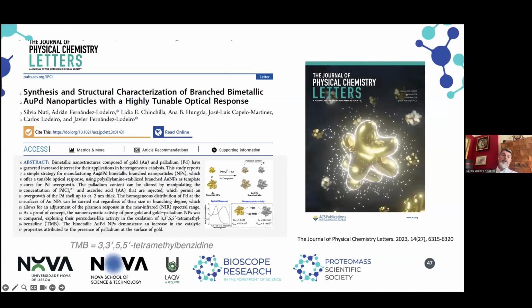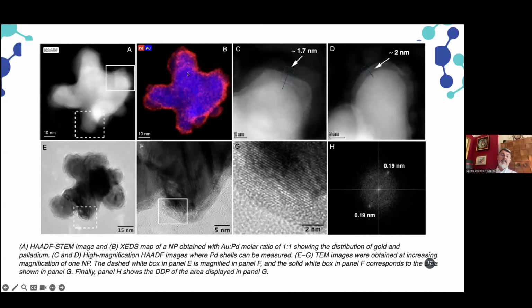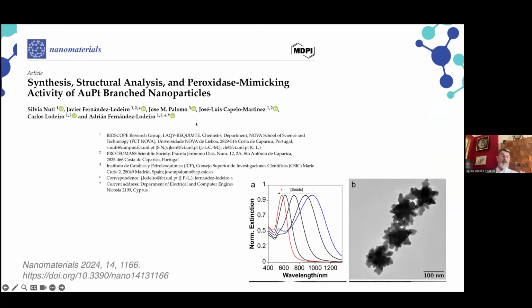For example, if you create the nanoparticles with gold and palladium, we obtain the same shape. We can modulate it so that the palladium is located outside of the nanoparticles, as I show you in these images. The STEM images show the red dots, which are the palladium atoms, and inside the stars are the gold atoms. So this bimetallic nanoparticle was again tested as a catalyst and works better than the pure gold nanoparticles. However, it does not do better than the gold-platinum branched nanoparticles.